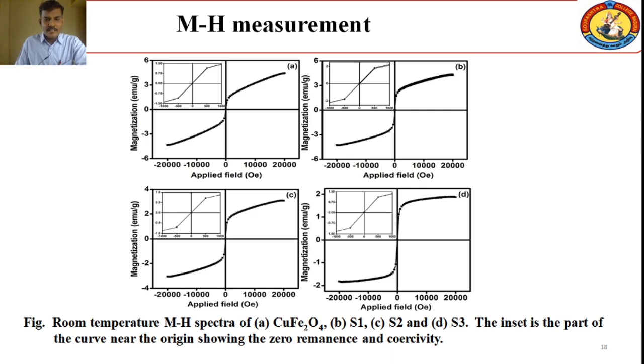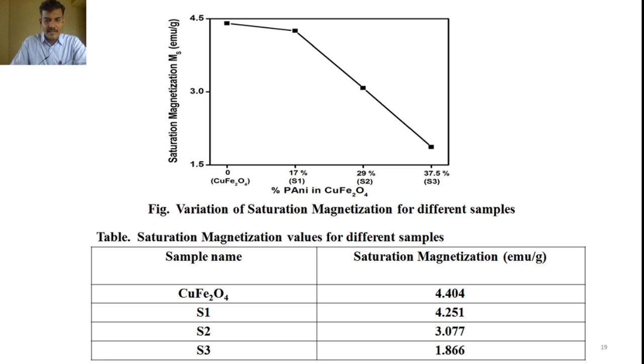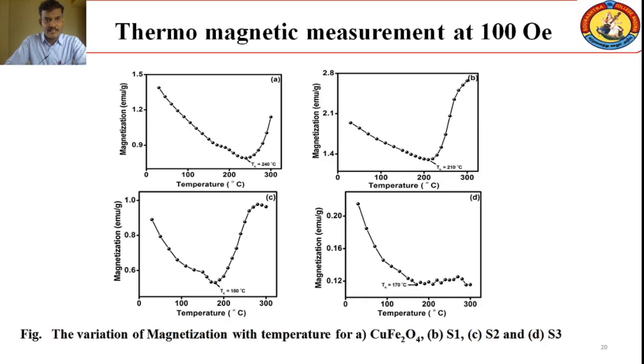The MH measurement of the copper ferrite and the nanocomposites shows a superparamagnetic behavior exactly at zero coercivity, and the saturation magnetization decreases while increasing the non-magnetic polyaniline concentration. Here it's a thermomagnetic measurement of copper ferrite and nanocomposites. When we increase the polyaniline concentration, the knee point value decreases continuously, which shows the non-magnetic behavior of the polyaniline material.